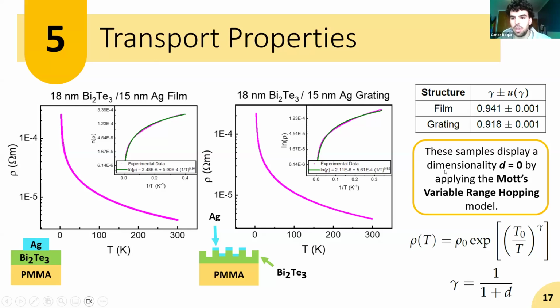Then we applied the Mott variable range hopping model, because it's the most adequate model for resistivity measurements in highly disordered systems. And we observe that our data exhibits a dimensionality of 0, which is often linked with quantum dots. So what we believe is that, as we already identified an amorphous structure in the X-ray data, our system has an intergrain resistance so big that it behaves as an ensemble of quantum dots.